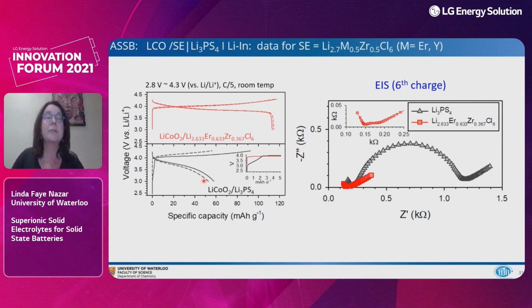This just shows over 2 cycles. And this shows for this cell the onset of that oxidation of the sulfide in the cell. And on the right, you see the impedance data in the cell for the 6 charge. And we're again comparing the situation for where we have the halide in the cathode.